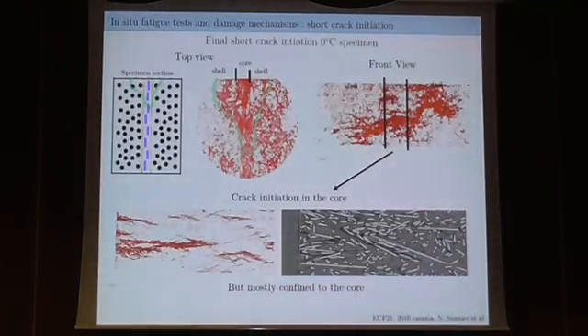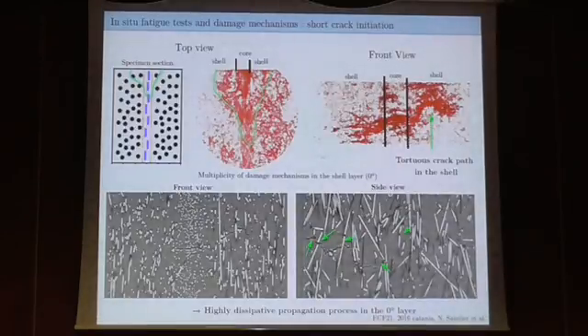While at 0°, that is a picture of the final crack. You see that you have in the core a lot of damage. This is a 90° layer. So a lot of decohesion between the matrix and the interface. You have a propagation in the core. It's only 300 microns, so you have propagation of damage, but it's constrained in this layer. It's very hard to propagate it in the 0° layer, and then the propagation is very hard in that direction. And you can see here that in the core, you observe the crack from the side. So you see it's propagating easily in the direction of the fibers. While if you go in the shell, you will have much more difficulty to propagate, and you have a lot of dissipation. So it means that you will have propagation in the core, very easy, but then to fail the specimen, you need to go into the 0° layer, and then it's very hard.